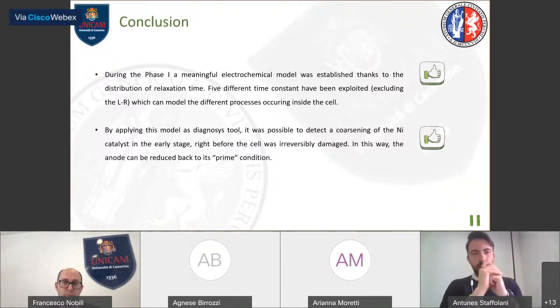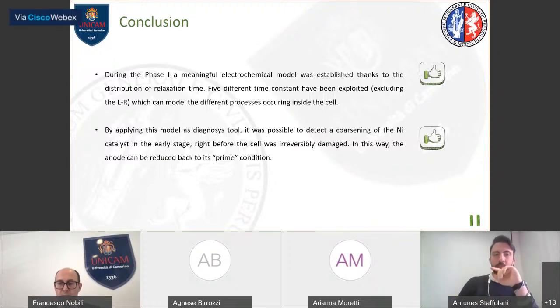So concluding, during phase 1, we established a meaningful electrochemical model thanks to the distribution of relaxation time. And we exploited the 5 different time constants, maybe excluding one coming from the inductor in series with a resistor. And by applying this model as a diagnosis tool, we detected a coarsening of the nickel catalyst in the early stage, right before the cell is irreversibly damaged. And in this way, the anode can be reduced back to its prime condition.